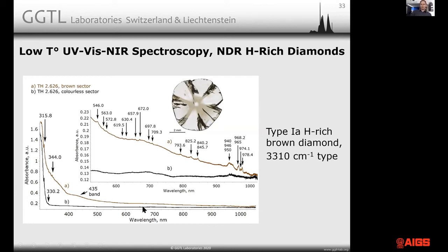The brown spectrum is a very shallow continuum with a flat band at 435 nanometers, virtually no N3 centers present at all. A couple of weak peaks overlaying the spectrum, most certainly, I would say, related to nickel. These stones, you put them in an EDXRF and you actually can measure the nickel in them. So they are relatively nickel rich. The color itself, I really don't know what it originates from, if it is possibly nano inclusions related. I'm not quite sure about that, but it's very different to what we know from other hydrogen-rich diamonds.